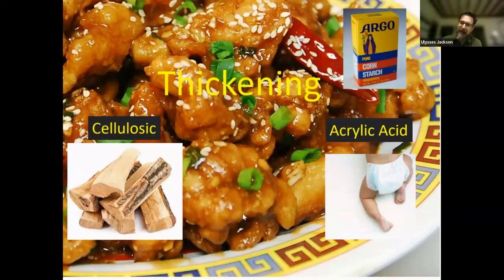On the other side, you have acrylic acid thickeners, going back to our absorptive material in the baby diaper. There are certain classes of acrylic acid thickeners used in water-based coatings that also swell or associate with a high pH system, allowing us to dial in with a very small amount of rheology modifier thickener to the consistency that an artist would like, whether that's an ink-like consistency like our high flow acrylics, or up to something like extra heavy gel matte that's a really thick paste.